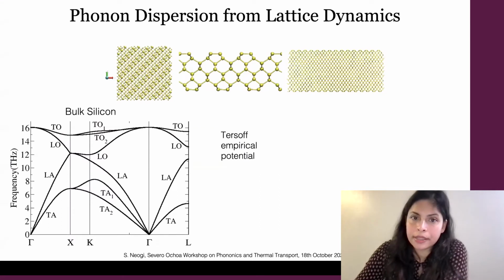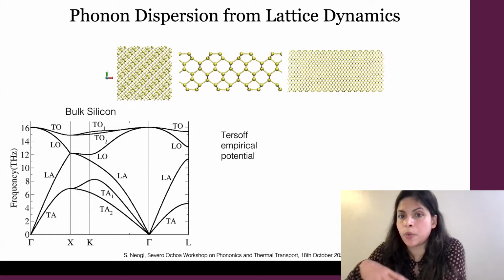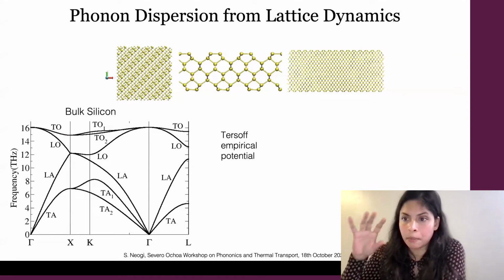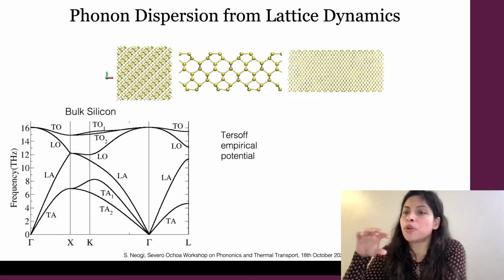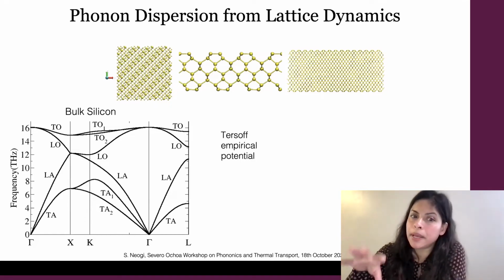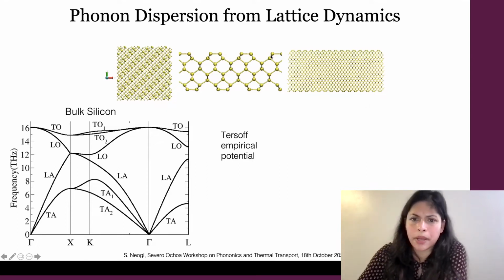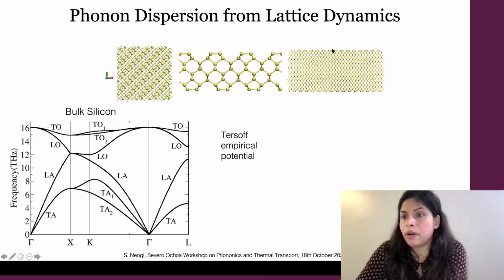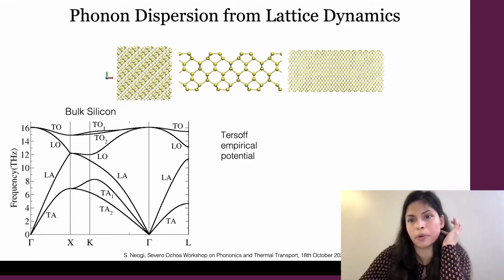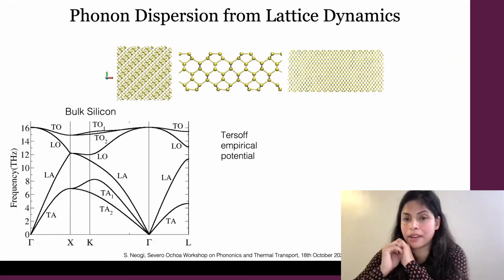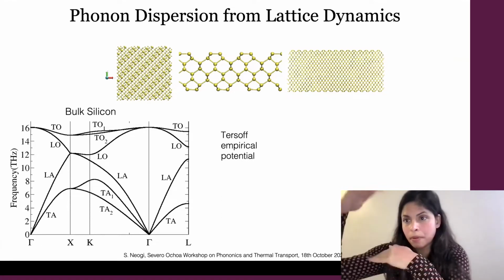So to get to further details, of course, we are going to lattice dynamics. And here we are looking at more periodic samples, much more well-behaved. It is harder to do with the oxide because of the amorphous layer, so we are going towards more ordered structures. First of all, this is the basic membrane with the dimers. I think this was 1 nanometer or something like that. Because of the presence of the dimer, your supercell or unit cell, whatever you call it, becomes huge because you have to include both the top and the bottom. So you take a slice of that as your supercell with the vacuum on top. The number of atoms you have to analyze grows pretty fast as you make the membrane thicker and thicker.